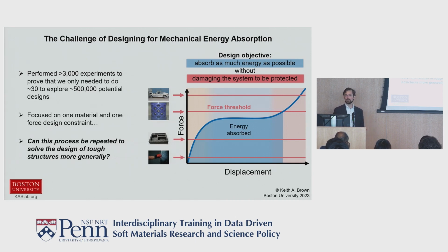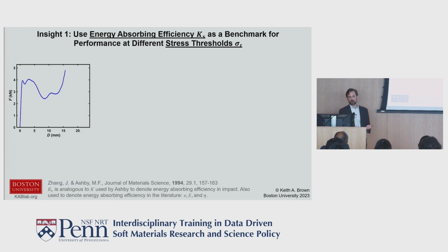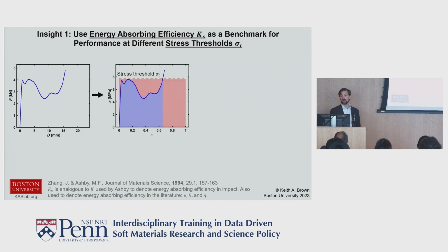And so for this, we need to change our thinking in a few important ways. The first thing I want to highlight is we changed from thinking about components in terms of their force displacement to thinking about effective materials. And to go there, we're going to talk about stress and strain. So we're going to use effective stress and strain of these materials. So you're thinking about an effective medium approximation. And when we do that, the first thing that jumps out at you is the strain goes to 1. This is because when you have a material in compression, you can't compress it more than 100% strain. No material left. And one thing that jumps out from that is if you look at the stress threshold, that forms a box, where this box represents the very most energy you could possibly absorb if you had a perfect material. So that's our theoretical maximum.